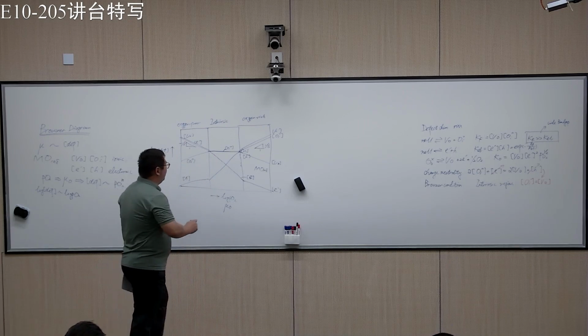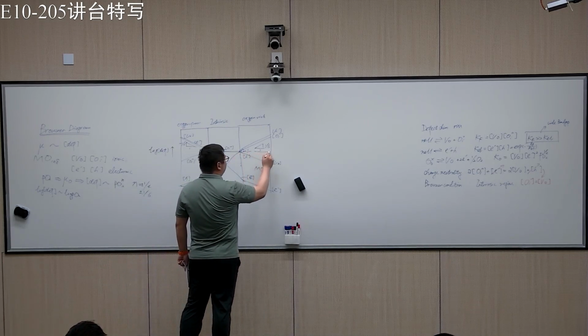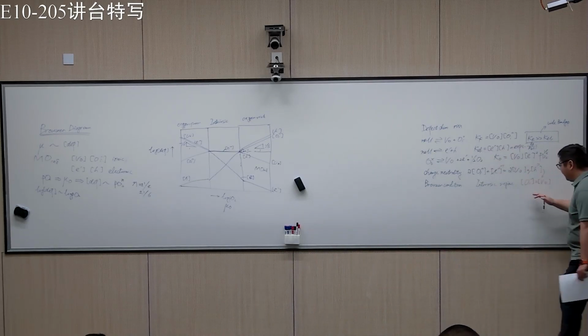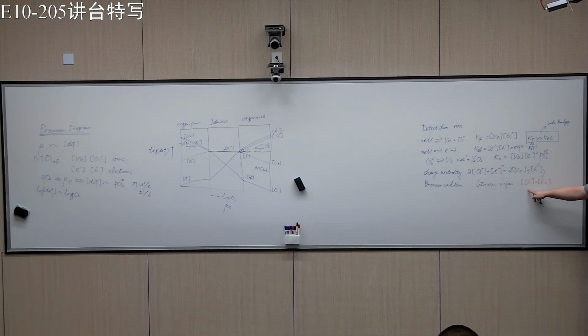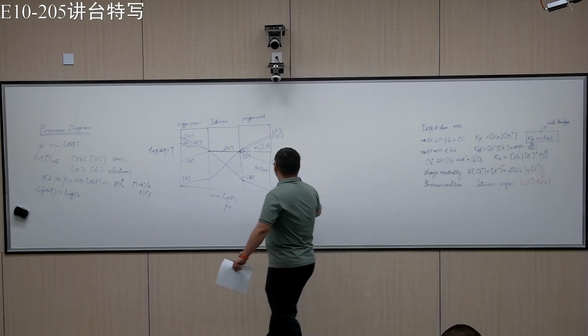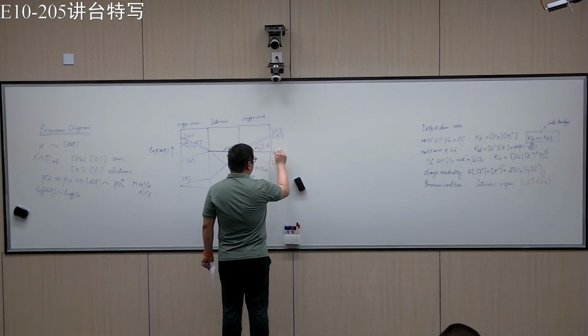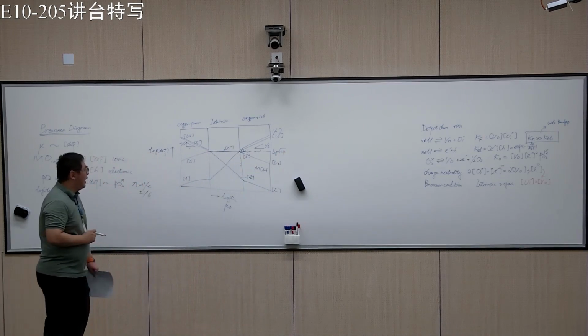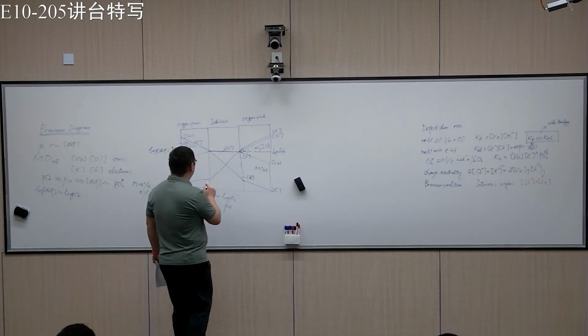So of course, we know that we can put the values into the plot, right? For example, we know that in the intrinsic regime, the number of oxygen vacancies is the same as the number of oxygen interstitials. And if we plug into this equation, we'll know that this is essentially logarithm square root KF. Okay. So we can also put other regimes into the equation.